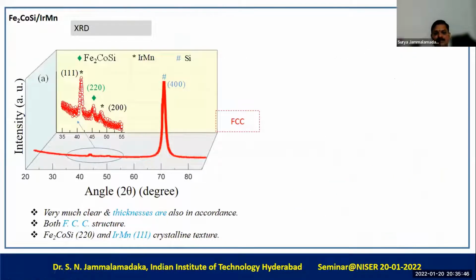So this is the GI X-ray diffraction pattern that we have obtained. It is very clear that we have both the iridium manganese phase and the Fe2CoSi phase in our GI XRD pattern. Also, the iridium manganese attains the 111 direction, and Fe2CoSi consists of the 220 direction.